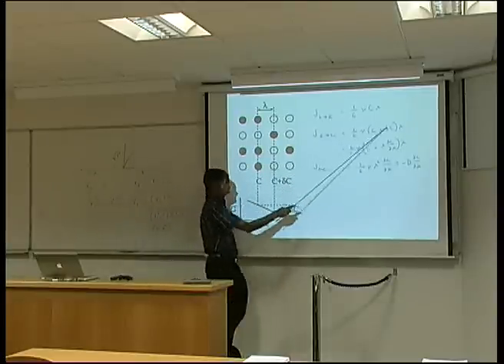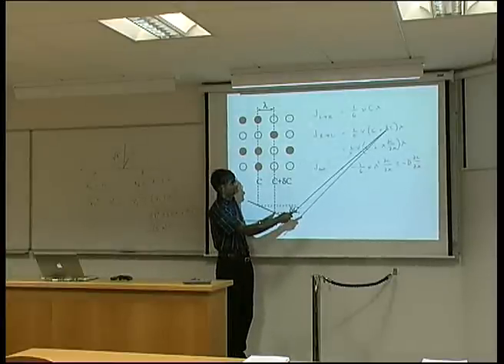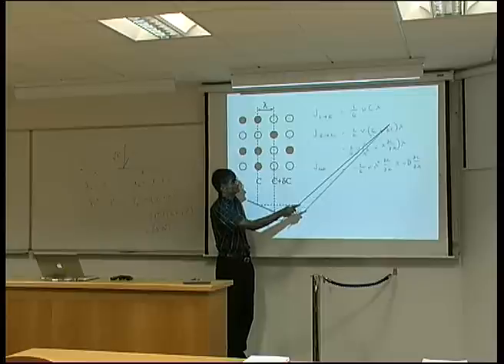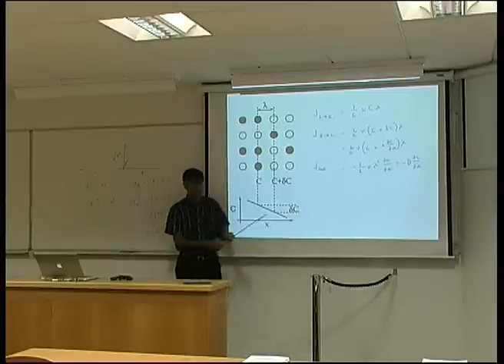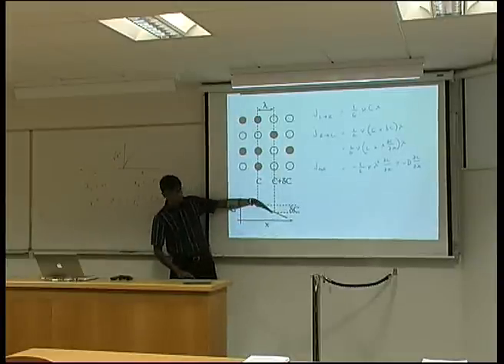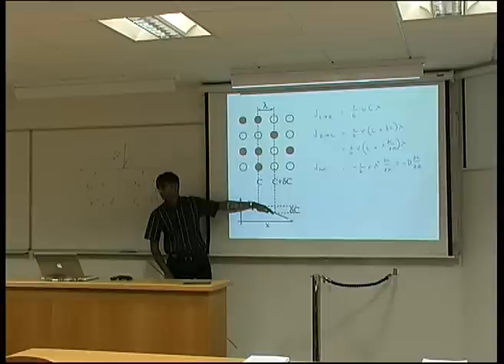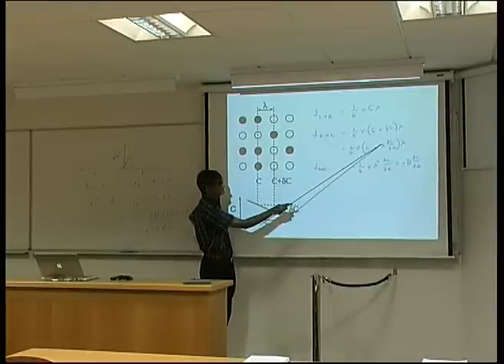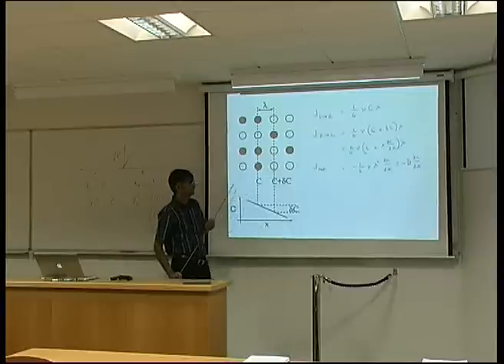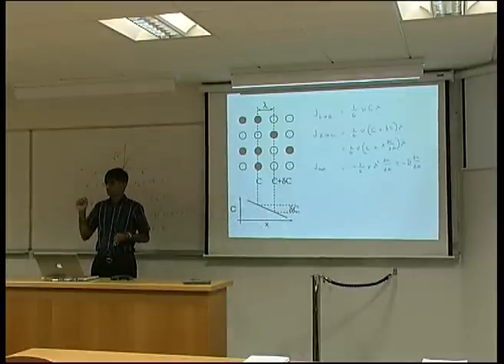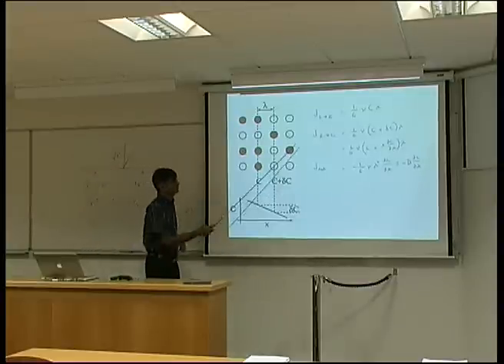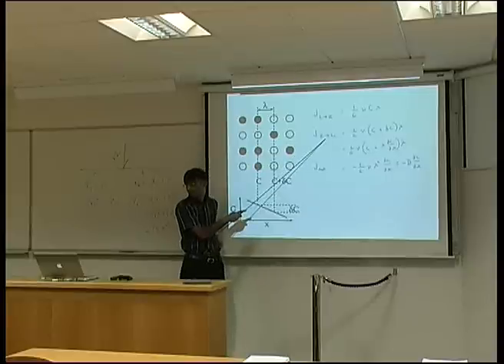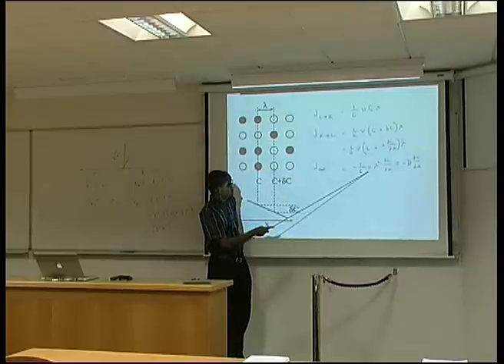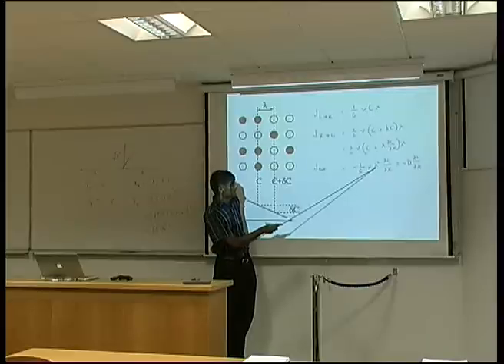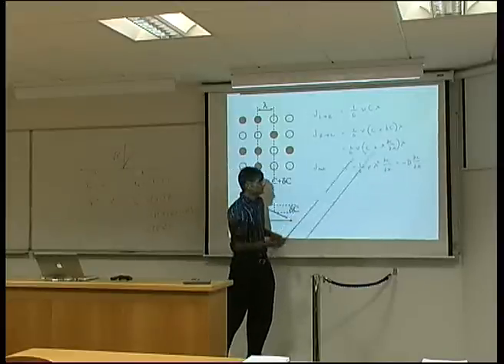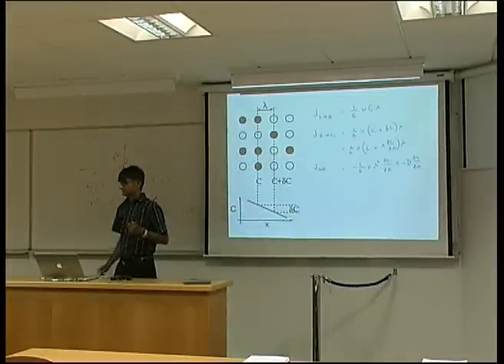Right, so the concentration in this plane is simply C plus delta C. And I can replace delta C by lambda multiplied by dC/dx. In other words, lambda is the distance along here multiplied by the gradient here, gives me delta C. Right? So I get C plus lambda times dC/dx, times lambda. And now the net flux along the x direction will be the difference between these two values. In other words, this take away this, which comes to minus 1/6 times the jump frequency, lambda squared dC/dx, and we write that as minus D times dC/dx.